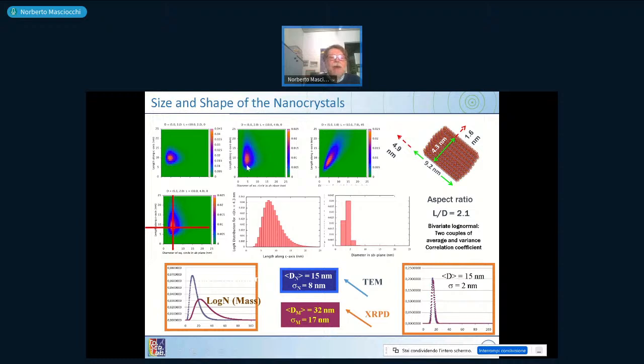Or you can have other cases where this kind of image is extended vertically. That means that all the crystals have about the same width but different length, or the length and width are correlated. So these are normal outputs which can be obtained by the bi-log-normal analysis, which we'll show later. And if it's non-dispersed, if you look at one direction only, you have a log-normal function which is encoded in our programs. And here you see only a tiny histogram because this is a log-normal function sampled at only 3 points. This is much narrower than the other ones here, so this explains why this kind of flame is narrower in a horizontal direction and larger in a vertical one. So these are just sections of this bi-log-normal system.